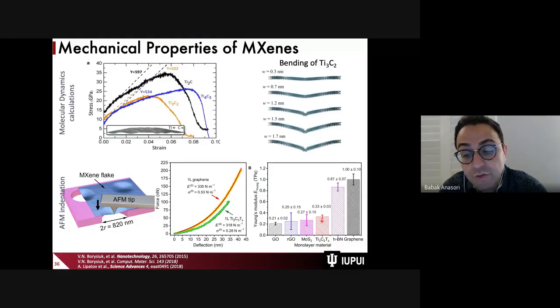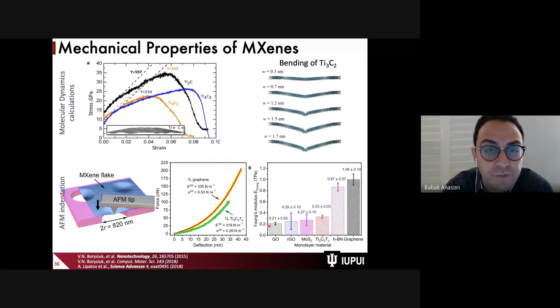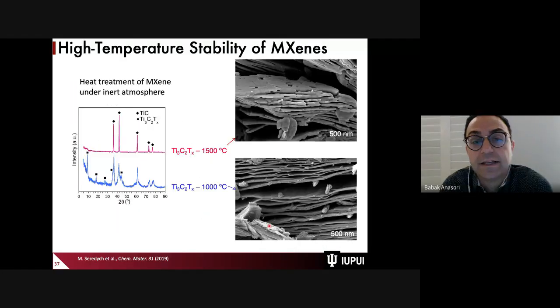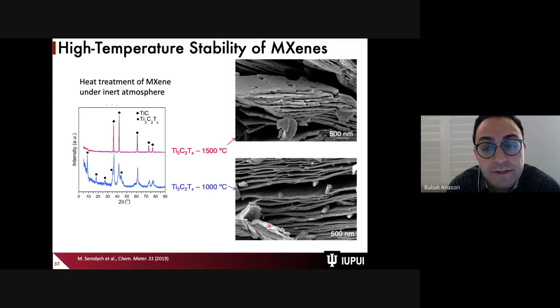It is very similar to graphene oxide or reduced graphene oxide, but if you look at the numbers, when we go from graphene to graphene oxide, we go from 1000 to 200 gigapascal. That's where MXene outperforms all other solution-processed 2D materials or nanomaterials that we can make at large scales, and they are hydrophilic, ready to bond. Also, even beyond that, MXenes, as transition metal carbides, if they are in a controlled environment, are high temperature materials. So we can integrate them, put them in metals, possibly put them in ceramics, and then use them for high temperature applications, which is the nature of transition metal carbides.